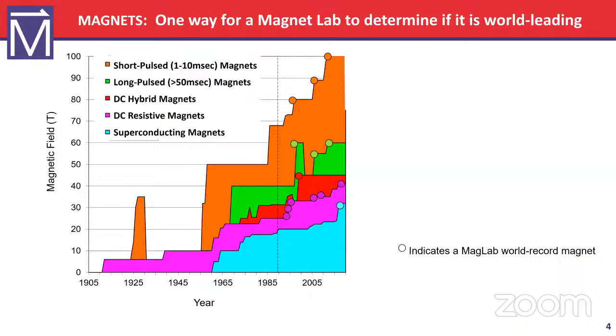And then if you want to go to higher fields, you have to pulse the magnets. You turn the magnet on and off rapidly enough that it doesn't melt. And you don't create 5 tons of molten copper in under a second. And if you have your pulse lasting more than 50 milliseconds, you can get to 60 Tesla. If you're willing to do your experiment in 1 to 10 milliseconds, you can actually get to 100 Tesla. So each of these circles is a MagLab world record.